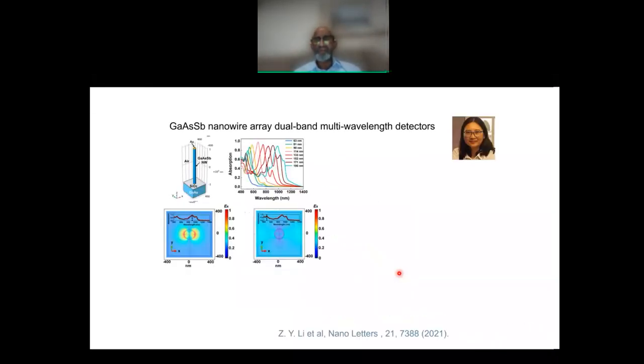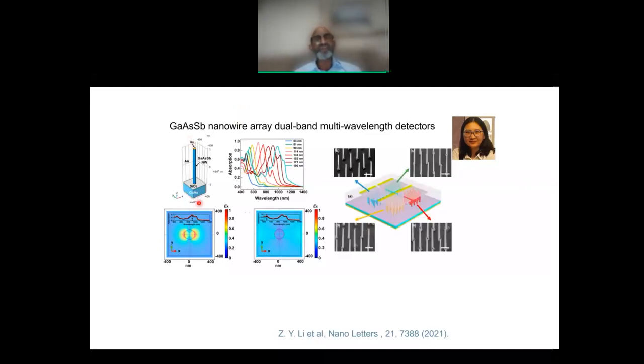This is the work of my young colleague, Dr. Xiong Li. She has been taking individual nanowires and creating nanowire arrays, because each nanowire acts like a resonator, for example. So by changing the diameter of the nanowire, you should be able to tune the detection wavelength, because the resonant wavelength is very much dependent on the diameter of the nanowire, for example.